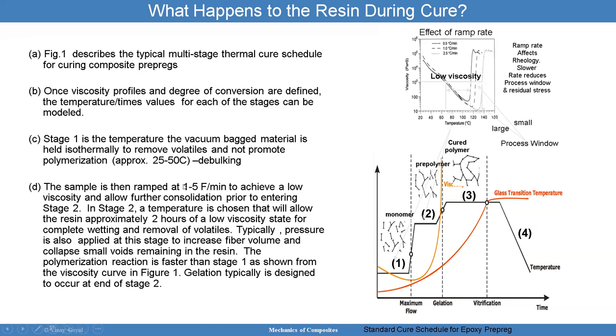And then I go ahead and take the sample and ramp it up 1 to 5 Fahrenheit per minute to achieve a low viscosity and allow further consolidation prior to entering stage two. In stage two, a temperature is then chosen that will allow the resin to basically have a low viscosity state for 2 hours. And you're doing that for complete wetting and removal of volatiles. So again, you're letting the resin flow in a nice way. Typically, you want to apply pressure at the same time to increase fiber volume and remove any remaining voids in the resin.